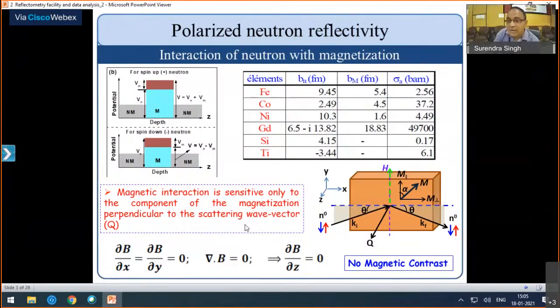It is like a non-magnetic sample only for neutron. So we can get depth profiling information in ferromagnetic materials, because all those other things will be treated as a non-magnetic sample, since average magnetic potential in those cases is 0.